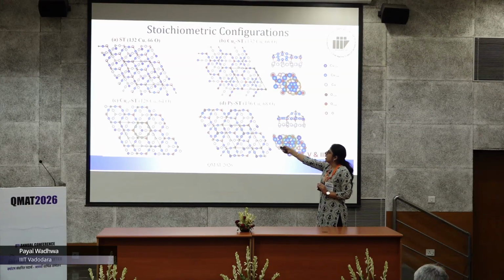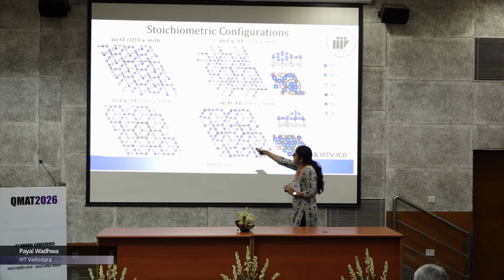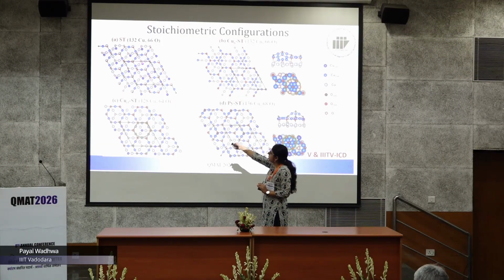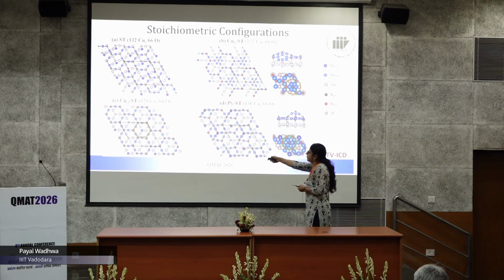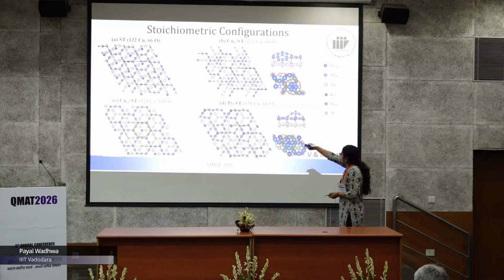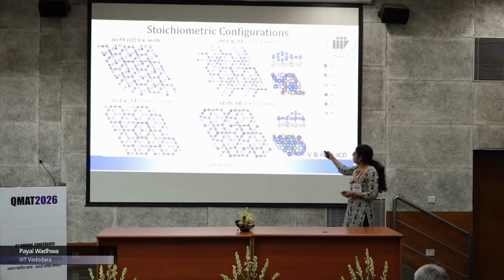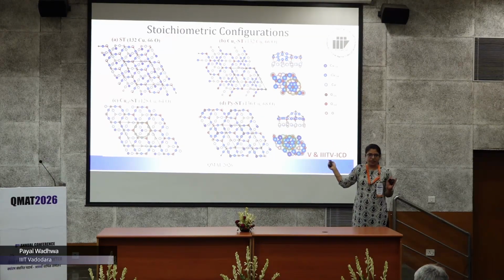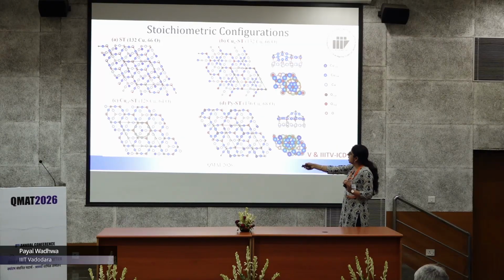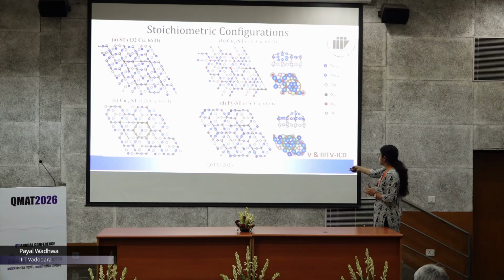So this was the original stoichiometric configuration. When we relaxed this structure using the machine learned force field, you can see here that this is a simple hexagonal structure with the center atom a little bit distorted, a little bit away from the center, meaning it is breaking the center of inversion symmetry. And when we performed the global optimization on the same stoichiometry, we found this copper cluster. Of course, you can never predict this kind of structure using DFT if you relax it. And then we performed global optimization, that is parallel tempering, on other stoichiometries as well, and this kind of copper clusters we got.